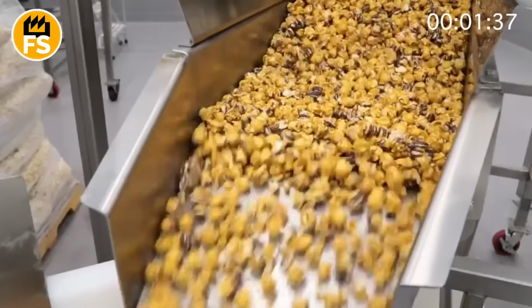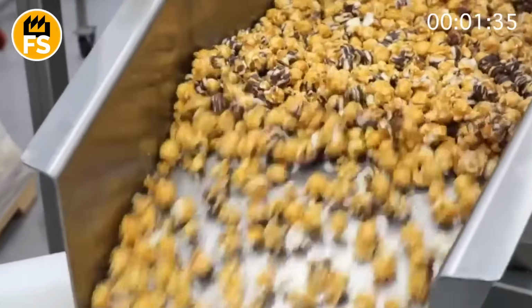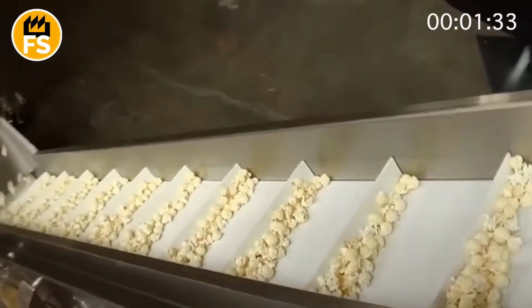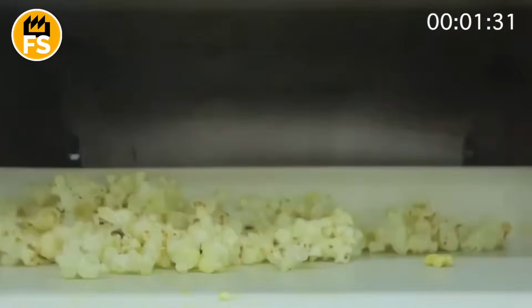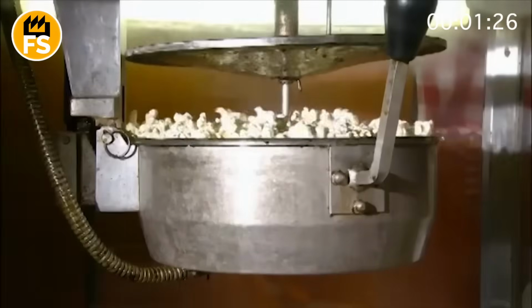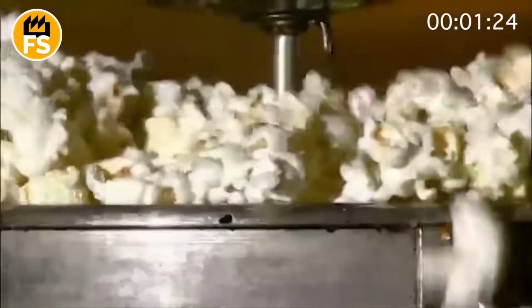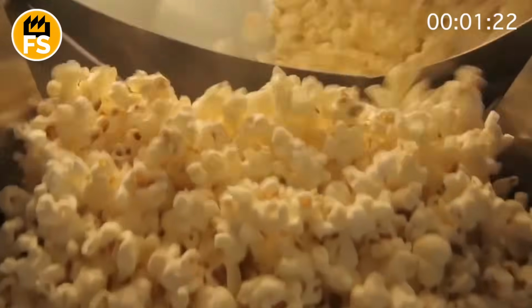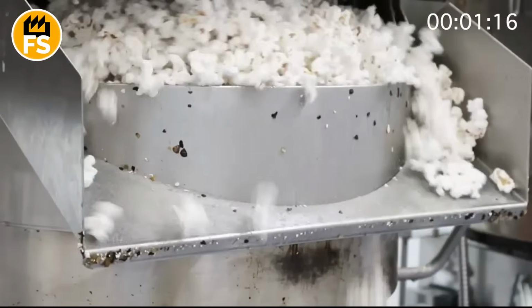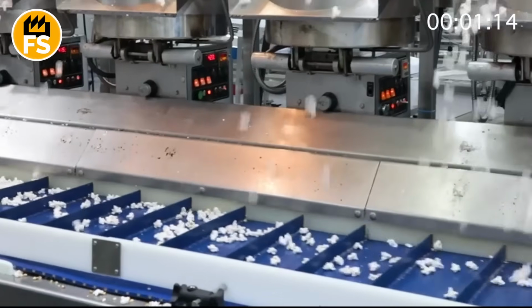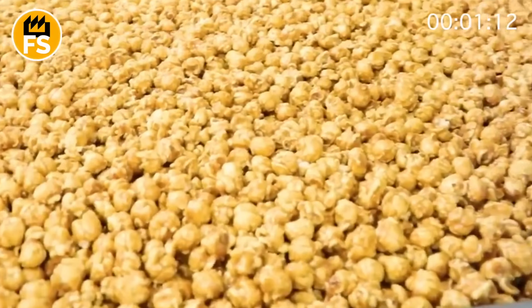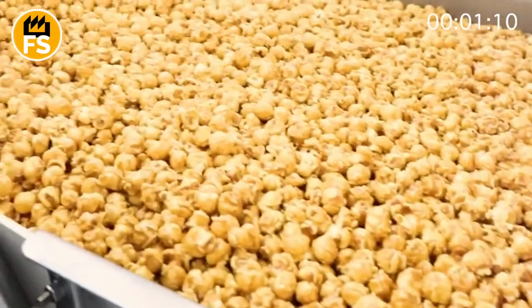Popcorn arrives from the poppers or caramelizers hot. The temperature can reach 300 degrees Fahrenheit. To prevent kernels from sticking together and ensure crispness, the product is immediately sent onto conveyor belts or screens that are ventilated with cold air. The flow of cooling air is controlled by a computer that adjusts the temperature and speed according to the volume and type of popcorn. This allows a large batch of 500 or 1,000 pounds to cool down in 5 minutes